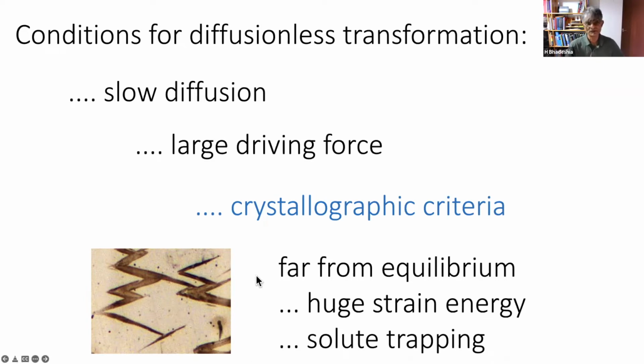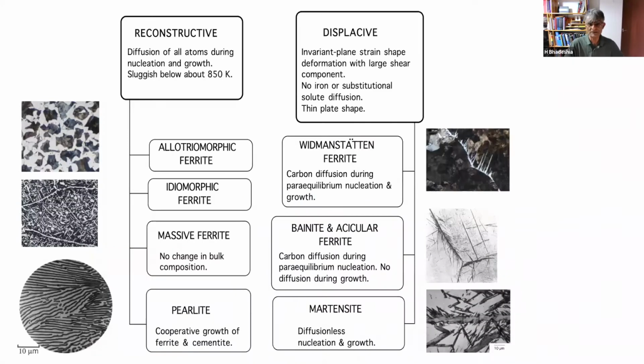Okay, so displacive transformations like martensite will be far from equilibrium, with a huge strain energy, and it's that strain energy which makes them adopt a thin plate shape with a sharp tip, because that accommodates the shape change very nicely. And we will get solute or solvent trapping inside the product phase. Now, if you look at typical steels, not special steels, then there are all these phase transformations that can happen, and they can be classified into displacive and reconstructive transformations. All of these are much closer to equilibrium than all of these.